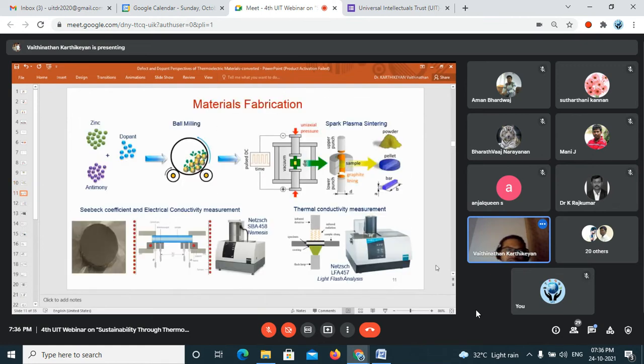So this slide shows how we fabricate the material. We take zinc metal and antimony metal powder. Then we add a certain percentage of rare earth dopants, and then do a high energy ball milling process, where these are mixed in the particular ratio, and due to the ball milling energy, they combine together and form this structure. And then we pelletize using the spark plasma sintering technique, where the powders are compacted into a metal piece. It means that it has very high density and it's not like a powder.